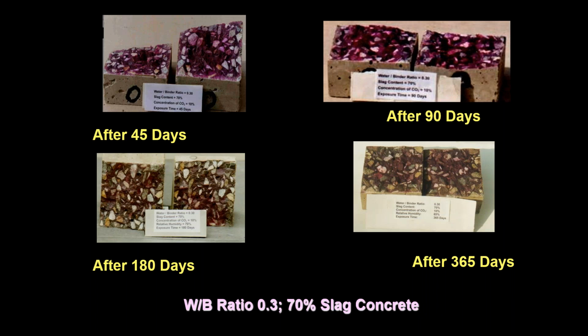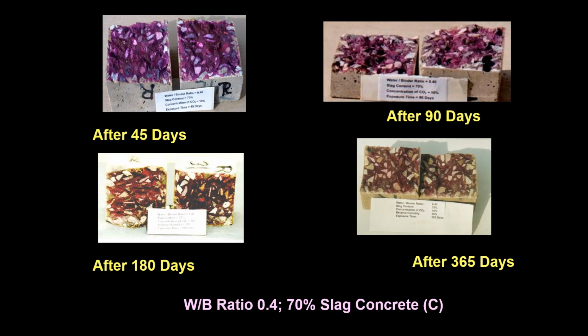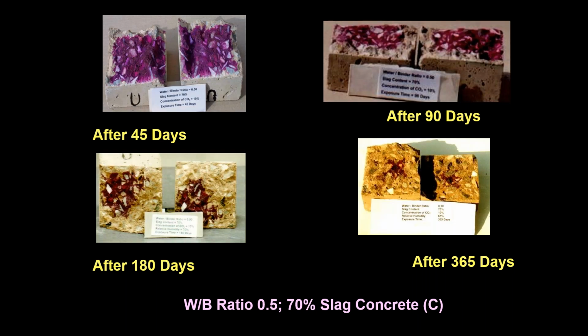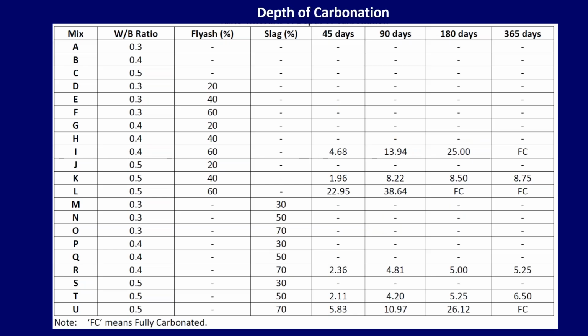And 0.3 water binder ratio, 70% slag, no carbonation. Yes, 0.4, 70%, there is a carbonation on the edges. It's quite an interesting case. Water binder ratio 0.5, 70% slag. Yes, there is a carbonation, fully carbonated. These are all the carbonation depths.